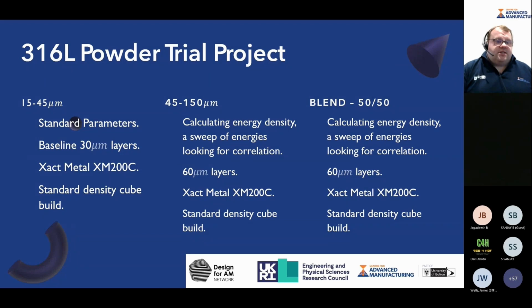So what we had was a standard 15 to 45 micron cut. We used our standard parameters, our Xact Metal XM200C, 30 micron layers, and we did what I call a standard density cube build, the builds that you've probably seen hundreds of times. Because of the nature of our investigation methods, we wanted to use PIP, which we've now heard lots about and hopefully understand. So we didn't need to do large full height builds. We could go for a short build with a quick turnaround time, about 2.5 hours for the build, about 25 minutes per coupon before we got some test data.